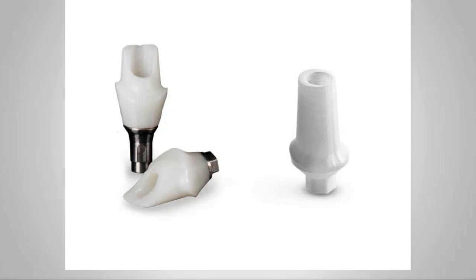The right side of your screen is an entirely zirconia abutment. Once again, this would be done out of a very high strength zirconia. You can see that the interface with the implant is also zirconia, so this is one piece. There have been some issues with fracture of that internal component, and you have to know the pros and cons to each. I think most people have gone to using the Ti-base hybrids like you see on the left side of your screen.